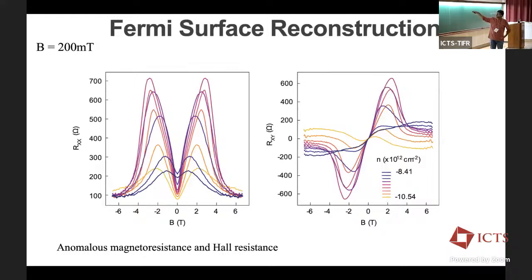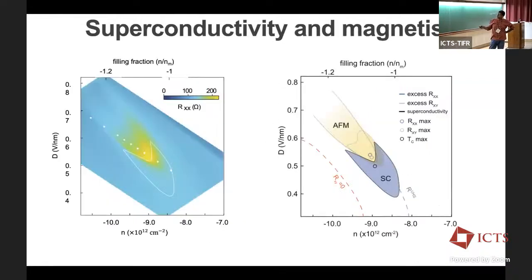I'm not showing you data at densities that are far away. That looks exactly the same as the previous samples. If you look at the longitudinal magnetoresistance, this also shows these interesting signatures that go along with the same field scales. So everything here in this particular sample points to the fact that we have an antiferromagnetic state that's right there in the vicinity of the superconducting phase.